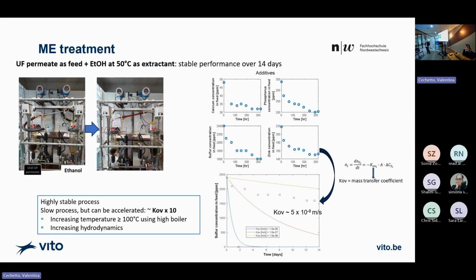It's going relatively slow. You see it here with ethanol, but the stability is very good. They tested it over 2 weeks, and we know by now that we can increase the rate of this process by going to high temperatures. So not using ethanol, but using high boilers like the NMP or the DMA, and increasing also the hydrodynamics.